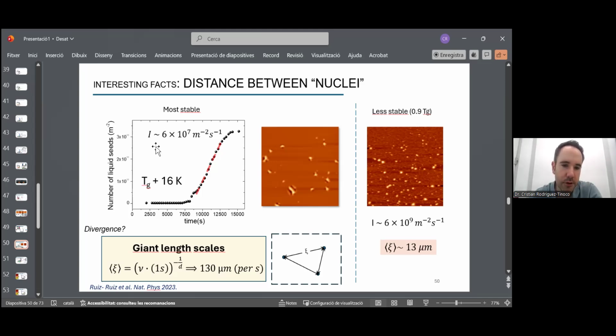We have this kind of plot, and from this slope here, we have the nucleation, let's say, frequency. If we do the inverse of this and we linearize, we get that for a unit of time, we have the emergence of these bumps at separated distances of 130 micrometers. So the distance between one region transforming into the liquid and another region transforming into the liquid at the same time is 130 micrometers.